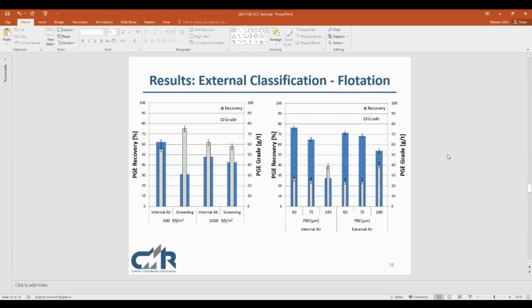So we also did flotation test work on these samples, not necessarily as interesting as the airflow test work, but we found that the screening products floated less well, or we got lower recoveries for them than the internal air classification test work. That is most likely due to the difference in particle size distribution, where we had a coarser component for the screening product and the internal air classification product.